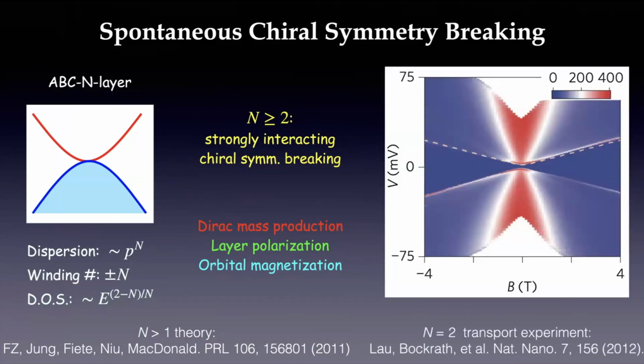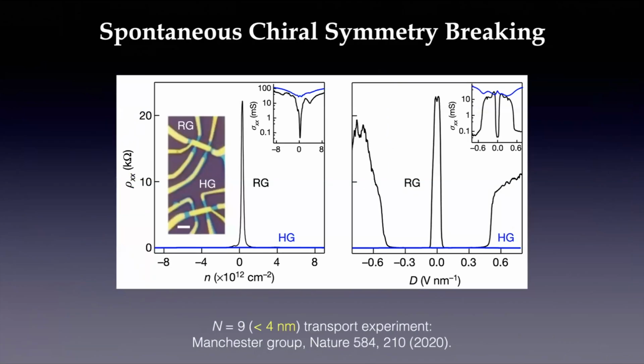Okay. So this is the first experimental data shown by Jeanie Lau and Marc Bockrath in the audience. Okay. So basically, transport spectroscopy measurement at zero magnetic field, zero charge density, zero electric field, there is a kind of gap opening right here. And later on, during the pandemic, the Manchester group did a more systematic study of this rhombohedral system, basically showing for the Bernal stacked system and the rhombohedral system, there is a very contrasting behavior. So for Bernal graphene, the resistance doesn't depend on the density and a perpendicular electric field too much. But however, there is a highly resistive phase at charge neutrality at 0 density, 0 magnetic field, 0 electric field.